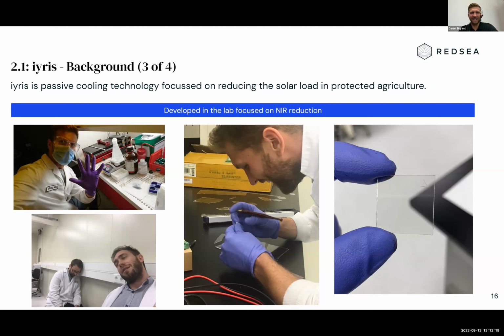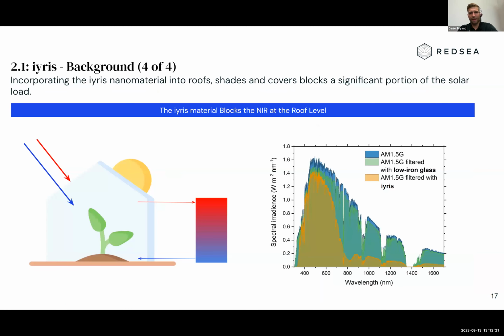So this is actually kind of where it started in the lab. If you look at this orange curve compared to the blue, and then the green would be a glass, for example, or you could have a polyethylene cover that would be very similar. You would drop a bit of transmission all the way along the spectrum. And you compare that to our materials.